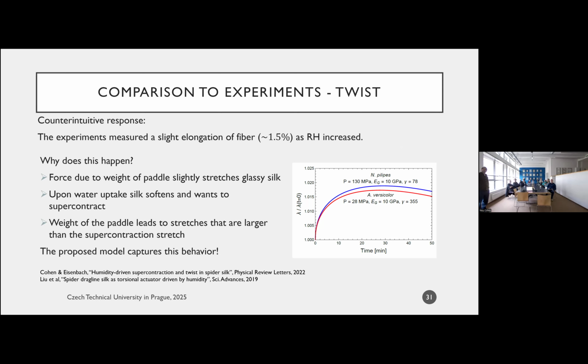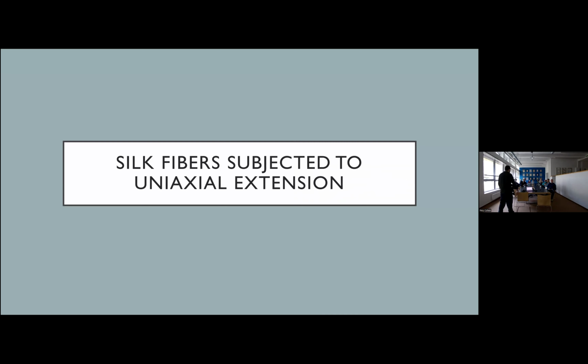You can see here, this is a function of time. We see that the fiber elongates, and the elongation itself is because there is a dead weight, and the softening is much stronger, if you will, than the supercontraction, right? Or the change in stiffness is much more dominant than the supercontraction effect. Okay, so after we had this, we figured, great, now we can understand the twist response.